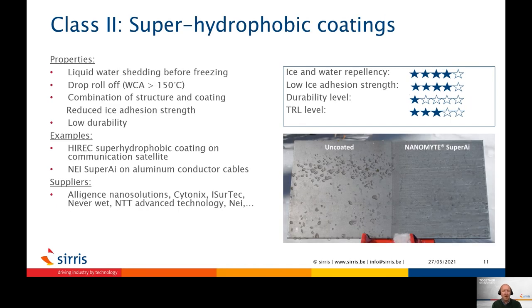A second class of coatings are superhydrophobic coatings, which are characterized by very high water contact angles and low roll-off angles. Such coatings are based on the lotus leaf effect, where water droplets just bounce off the surface due to a dual surface roughness in combination with low surface energy polymers. Several companies sell these coatings as anti-icing coatings, although they often lack durability, and application is limited to less demanding applications. Coatings are used to prevent snow and ice from forming on satellite dishes, conductor cables, or condensed units. In order to create more durable surfaces, there is ongoing research focused on the replication of structured surfaces with a larger durability level.